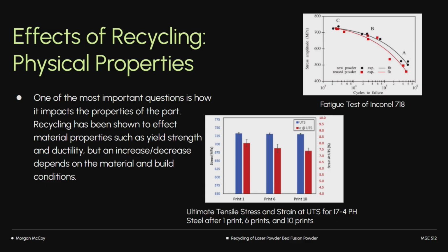Recycling has been shown to affect material properties such as yield strength and ductility, but an increase or decrease depends on the material and the build conditions, as there's a lot of variability in that. At the top right, you'll see a fatigue test of Inconel 718, where the reused powder has a shorter fatigue life.